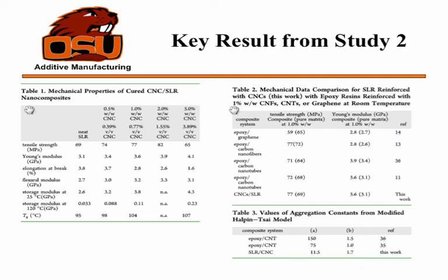When they introduced the cellulose nanocrystals into it, there was not much change in the viscosity. It was a very mild change in viscosity. So the glass transition temperature and the polymer properties were retained.